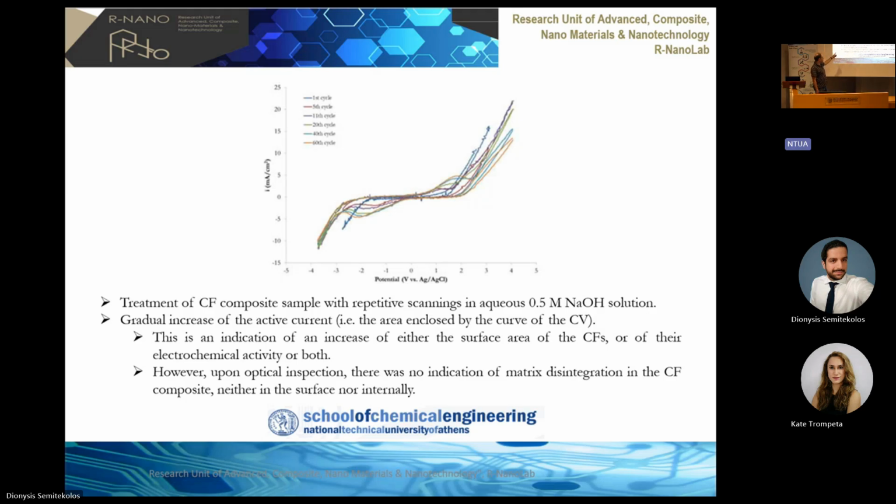And this is an indication that either the surface of the carbon fibers or the electrochemical activity changed, or both. However, upon optical inspection, there was no indication that the matrix disintegrated. The component remained almost the same.